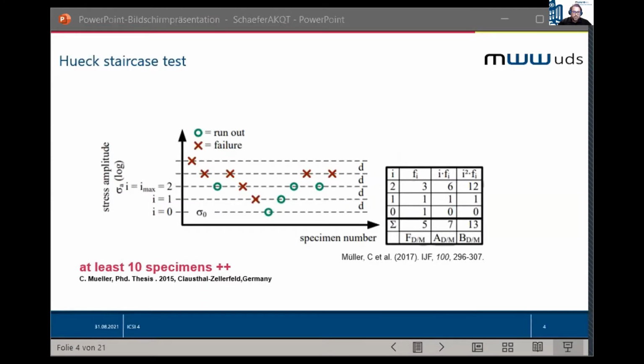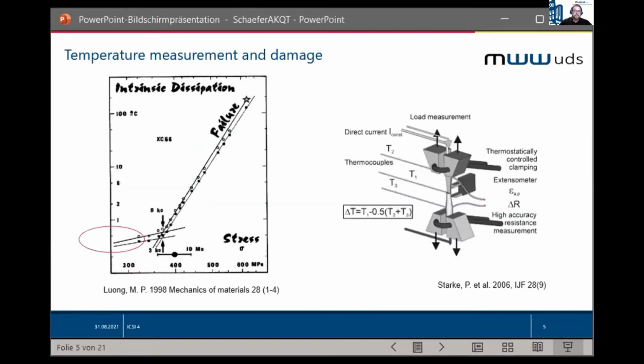And just to point it out, the one-specimen test for reliable fatigue strength is like the holy grail of fatigue testing. And for that goal, we want to use the heat generation inside the sample material, resulting in an increase in temperature, to characterize the energy dissipation, and hence to get an idea of the internal processes that correlate with damage. This correlation of the dissipated energy, the mechanical hysteresis, with temperature and damage is very old. Even in the 1920s, there were already first attempts. But new technologies such as thermography or sensors with large resolutions open up new possibilities.